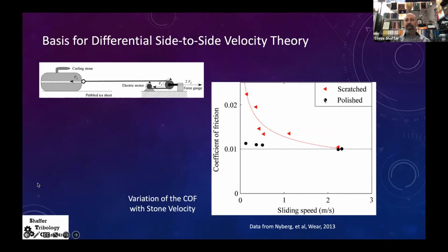And two things in this graph. One is that a polished stone, at high sliding speed, even down to low sliding speed, near 0, is around 0.01. So that's maybe an order of magnitude higher than what I calculated, but that was based on a constant acceleration or deceleration, and we know that that changes as it goes down the ice. And a scratched stone, and this is why we see them curl, the coefficient of friction changes, it increases as you get down towards 0 velocity. We observed this in curling and on that first video, that the slower a stone is going, the more it curls, and the coefficient of friction at the same time is going up.